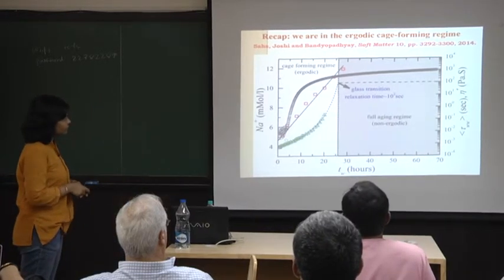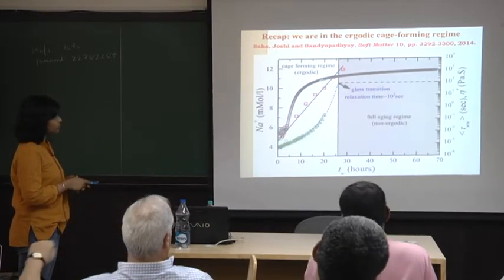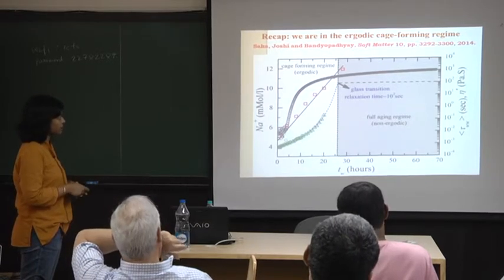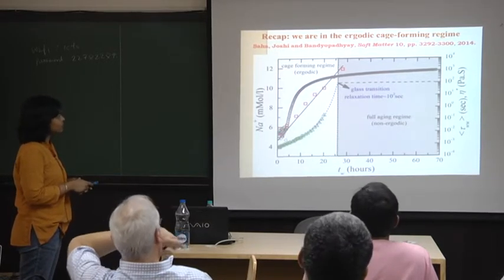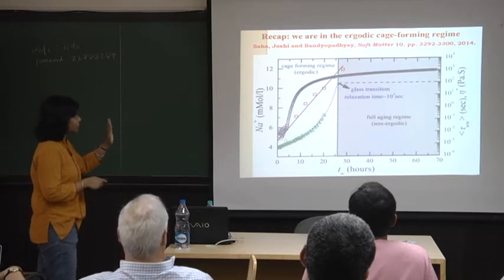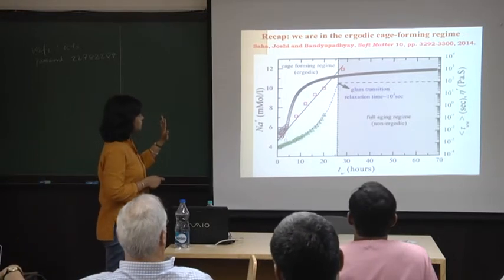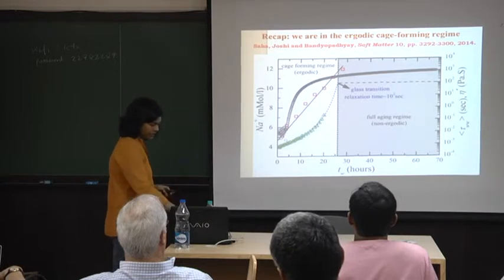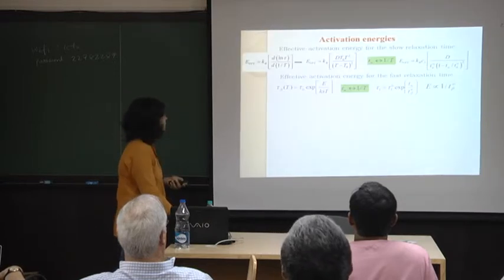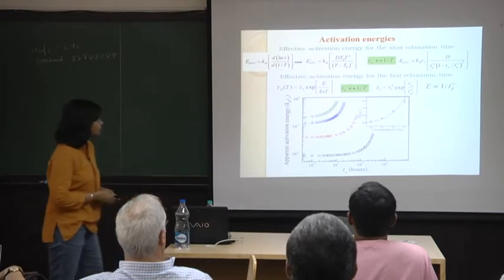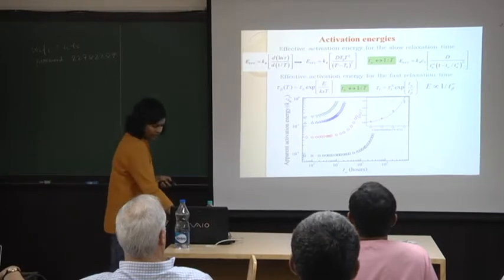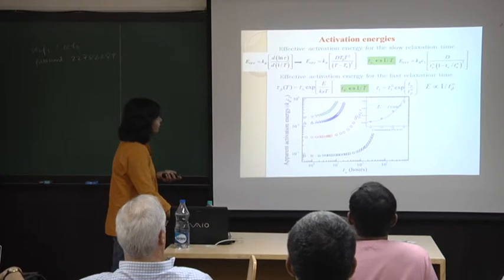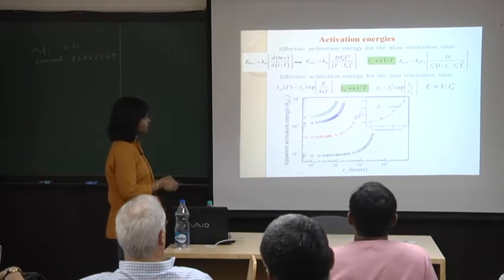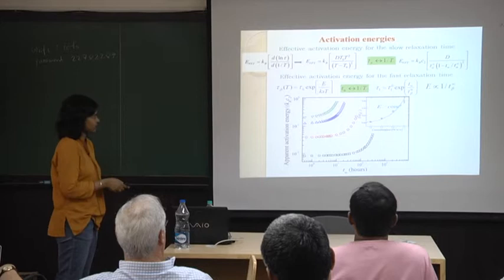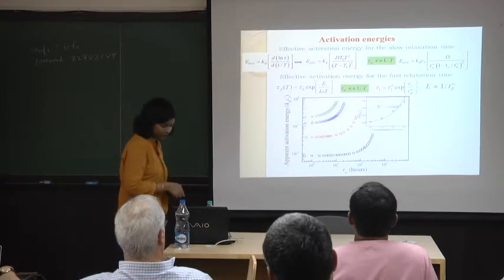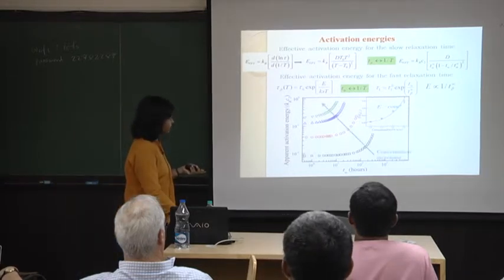These are the time scales that we have measured. This is the viscosity that you can also simultaneously measure as your system ages, and to us it indicates the presence of some attractive interactions. We've calculated the effective activation energies by doing our superposition. This is the activation energy that we've got for our fast relaxation process. Obviously it doesn't depend on the age of the sample.